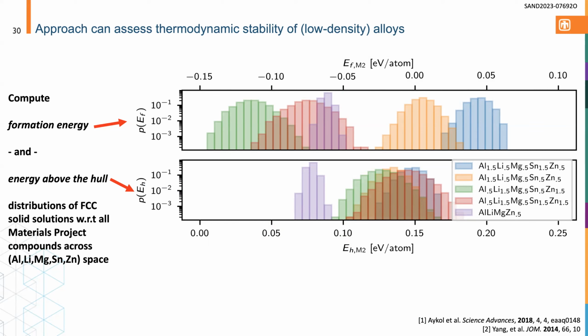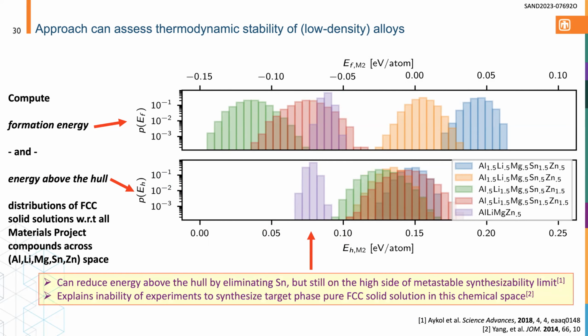We originally looked at this because there's an interesting paper that was trying to synthesize these low density alloys, but couldn't, and just speculated from experimental results why that was the case. If you do an exercise like this, you can clearly see there's no hope of ever making the material. We can reduce the energy above the hull by playing around in the compositional space, but no matter what, we're still on the high side of the metastable synthesizability limit. So pretty much no hope, and this explains why you can't make this material.